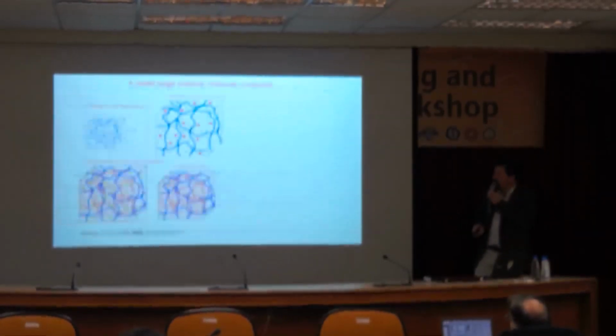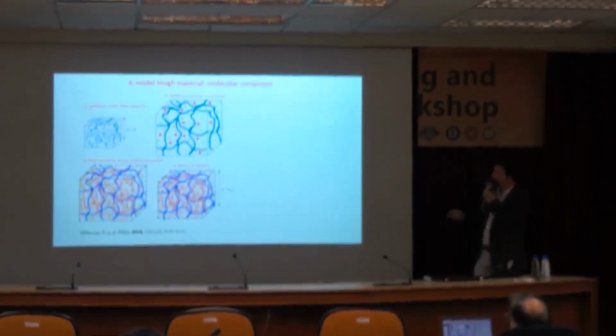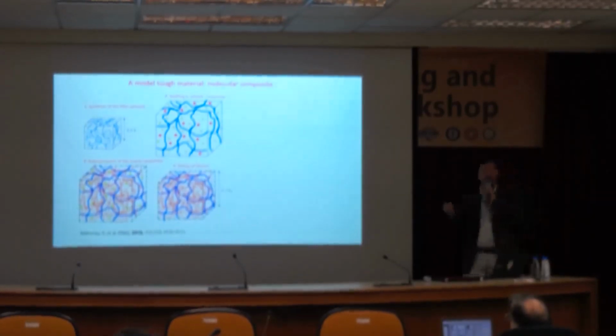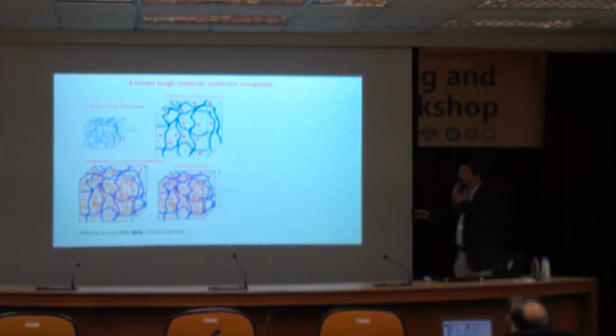So we're going to look at this one in more detail because in a way it's a simpler system. It's elastic. The other two have significant time-dependent behavior, which makes them more complicated. But this is still an elastic material, and it's really a molecular composite. So here is a little cartoon of how we make these materials. We're also chemists, so we make our own material. You start by synthesizing what I would call the filler network. You just make a polymer network by incorporating reactives and cross-linkers, so you're making something that looks like a mesh. Of course, these are all fluctuating random chains. We're above the glass transition, so it's molecules connected. It turns out that this type of network can be swollen by solvent, but also by monomer. So you can actually use a building block of the polymer to swell this material.